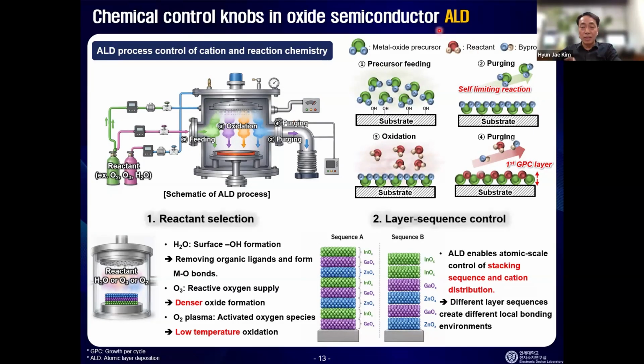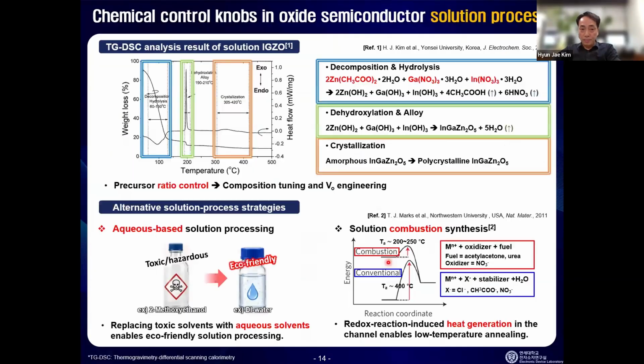This is relatively new. ALD is very famous for the semiconductor process. One more time, this is on a silicon wafer, atomic layer deposition. It's like chemical vapor deposition, but very controlled. You remove the gas after you have one layer of the material, one atomic layer. You purge and you oxidize and purge again. So you control layer by layer. So it's high quality. Okay. And they try to do reactant, I don't have time to explain all these things, but reactant selection or layer sequence. This is the way that they control the material.